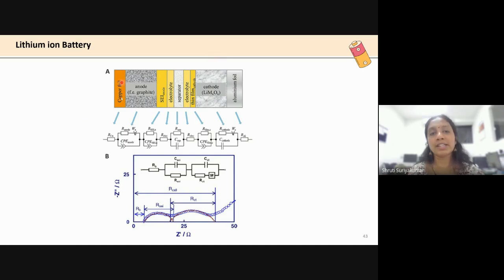So when you are to study a system like this, this is how you are going to deconvolute it based on the understanding that we have. But what we actually get is a combination of all these elements. So similar materials with similar time constants club together, and what we get are circuits like this. You have two semicircles. When you look at this profile, you must be able to see that there is a 45-degree region here that could be associated to mass transfer and diffusion, and then you can possibly deconvolute it to two circles, and we don't call them semicircles, we call them suppressed semicircles. They're not identical. Since they're suppressed semicircles, we can associate it here. They've given it as a capacitor, but I think you can use a constant phase element to fit it. It will be much better.